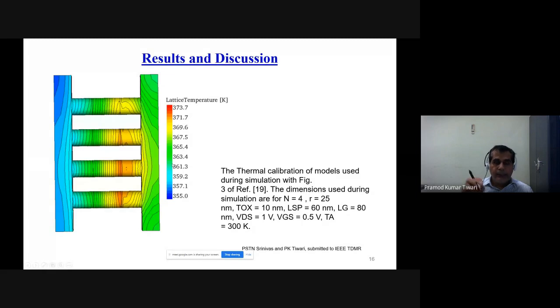Means at each and every point of the device, you can estimate how the temperature is varying. Here you can see that near the source and drain and channel interface, the temperature is highest, which is 373 Kelvin. This simulation was carried out at an ambient temperature of 300 Kelvin. What you see is that hot spots are actually built in the device. The hot spots are the regions where the temperature is highest. You can see the peak temperature goes up to 373 Kelvin, while the normal room temperature was 300 Kelvin.